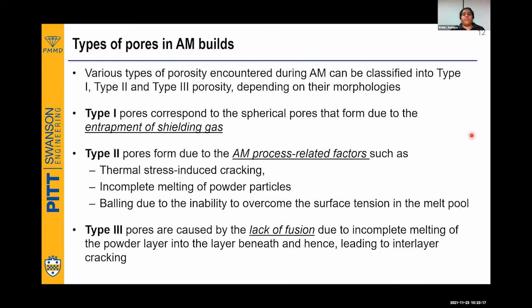The type 1 pores are perfectly spherical pores that form due to entrapment of shielding gases. What happens is the gases get trapped within the melt pool, and are not able to escape due to the vapor pressure. It could also be due to the powder composition. Let's say there is heavy oxygen or nitrogen content, or the powder got oxidized. We generally use gas atomized powders, argon atomized or nitrogen atomized powders. In that case, the nitrogen gas could form. So all this is going to create these spherical pores.